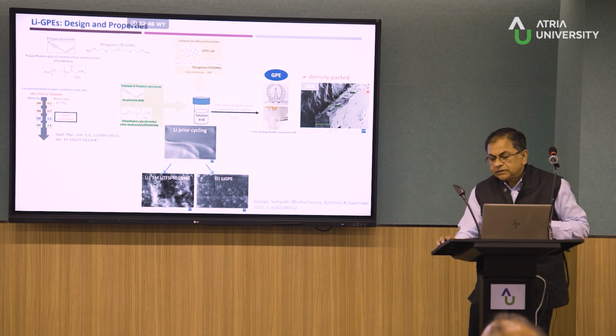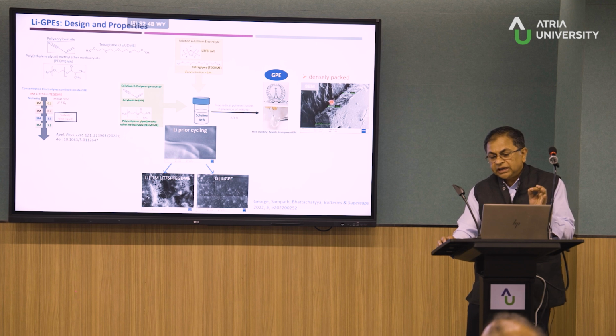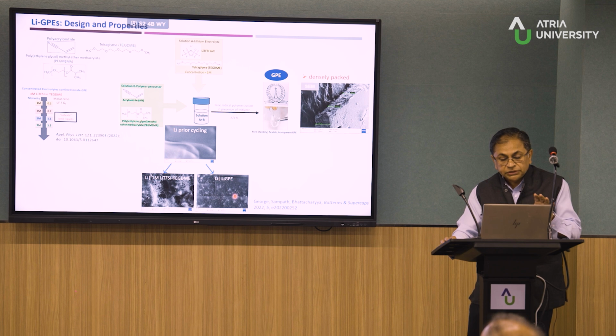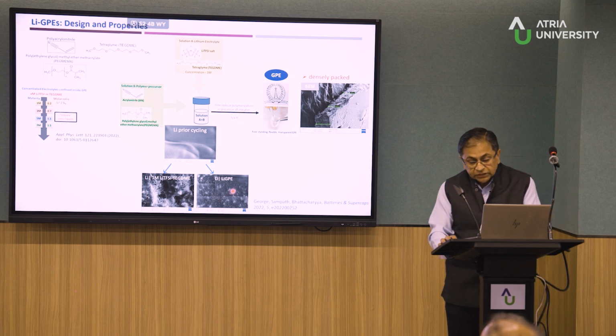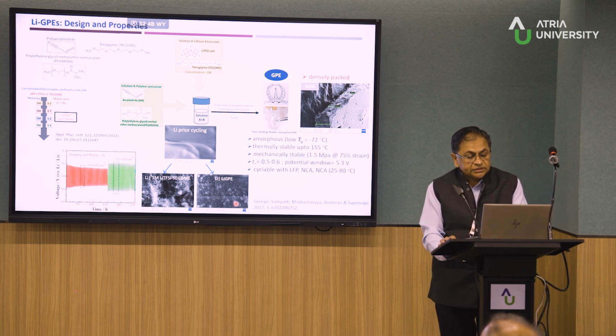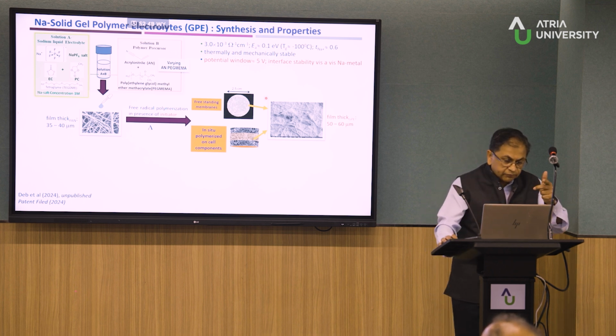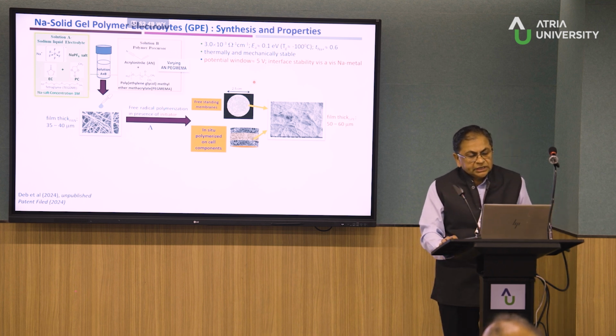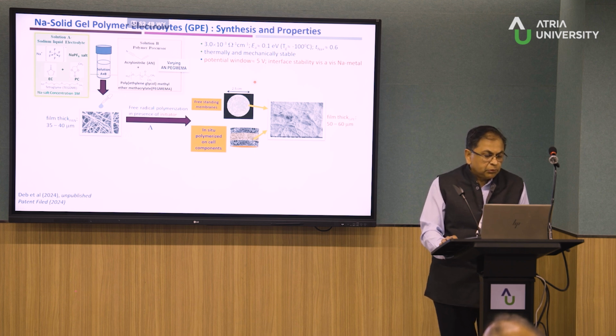Okay, as you see, this is a compact membrane which makes a very good contact with the electrode, and you run it for several thousand cycles. The liquid electrolyte is failing because you start getting dendrites, but here you actually don't see any dendrites. Okay, and then this is sort of lithium example which we did, and here are some of the properties. You can actually plate strip lithium for several hours at various current densities. Okay, a slight modification we did. This is for more applicable to sodium, but we can also do the lithium.